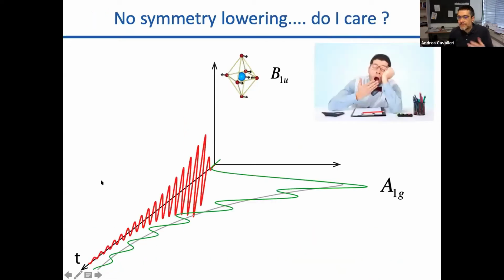So this may look like not a particularly exciting way to drive a material. Of course, I take a material in negative times, I drive a specific mode, I do all this work to drive a distortion, except that in these conditions, I can drive distortions that preserve the structural symmetry of the material, which is not exactly what I had in mind when I was thinking about driving a phase transition into a solid. So we will have to find more sophisticated protocols to do this, but for the purposes of this introduction,